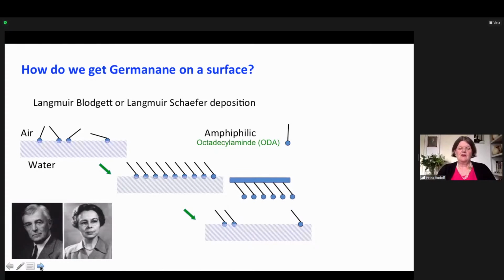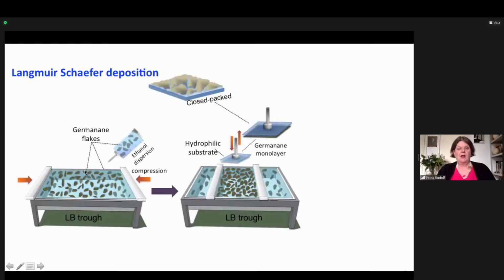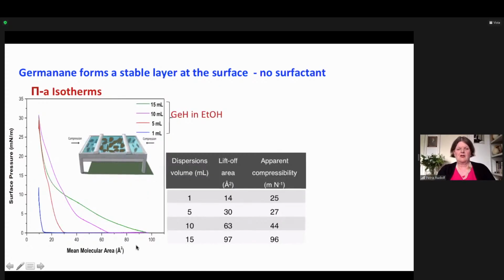So you can do the same thing with graphene or with germanane. With germanane, it's particularly simple. You just disperse germanane in ethanol, you deposit it at the surface, it floats, you can compress it to get the packing of the layers, then you come with your hydrophilic substrate and you pick it up and you get a close packed layer. As I can show you, this is a stable layer.